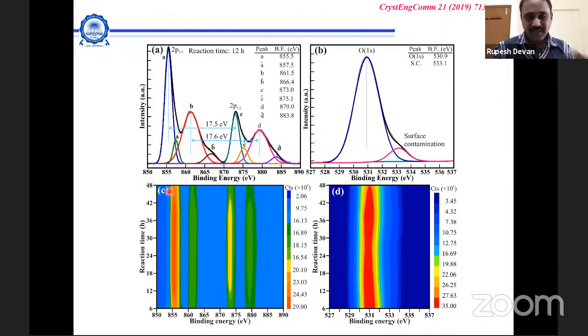And then we checked: when we change the morphology, does NiO remain intact, or is it in a suboxide form? If you look at this 2D format of XPS, the spectra remain constant even though you change the morphology. That means when you change the morphology, your atomic arrangement, or you can say the chemical composition, does not change. It remains NiO, it remains the same.